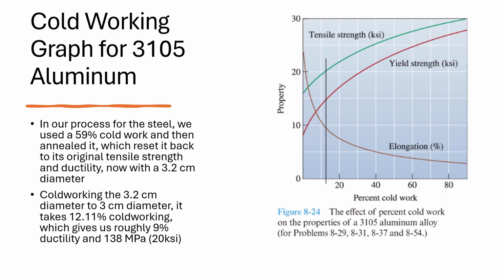Now cold working from 3.2 centimeters to the 3 centimeters, it takes only 12% cold working, which gave us roughly a 9% ductility. From looking at the graph, it was roughly 9%, and it came out to be 20 ksi, and converted to MPa, it was roughly 138 megapascals. If we were going to compare this to the steel constraints, it wouldn't fit even close. The ductility was well below 15%, and the tensile strength was greatly under the 800 megapascal mark.